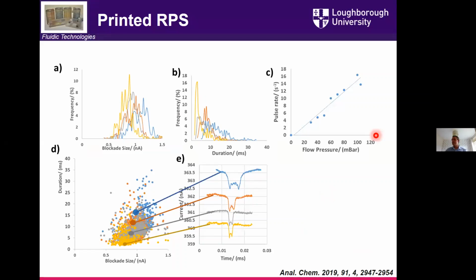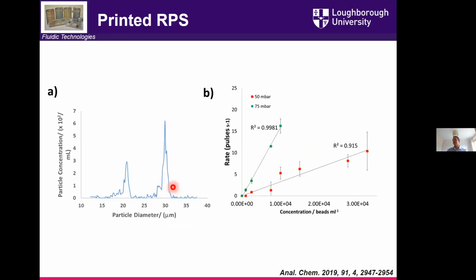And so as you make those 3D printed resistive pulse sensors, you can change the flow rate. You can look at how many droplets pass through per second. You can calculate the concentration and number of droplets you're making. You get a measure of the speed at which they go through, so you can measure flow rates. You can characterize their size, as you would expect in those measurements, and they're very accurate for different sizes. So you can have droplets of different sizes within your system, and you can characterize them in that way.